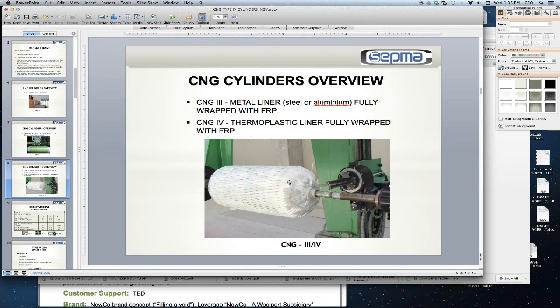Then we pass on to the Type 3 and Type 4 solutions. This is an example of a Type 3 here. The difference between the Type 3 and the Type 4 is in the type of liner used in the technology. So, for instance, in the Type 3, we'll see the use of a metal liner, typically aluminum. It will be a unibody solution where the aluminum will be typically about 4 millimeter thick. So it's not going to be very thick at all, and it's not going to be a load-bearing structure, but it's simply used as something to wrap your fiber onto, and also be inert with the gas that it carries.